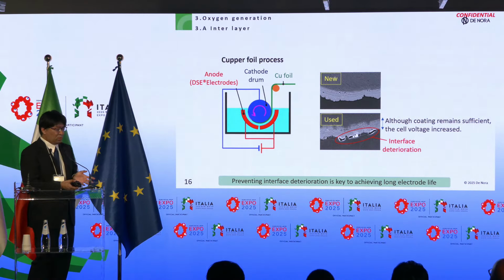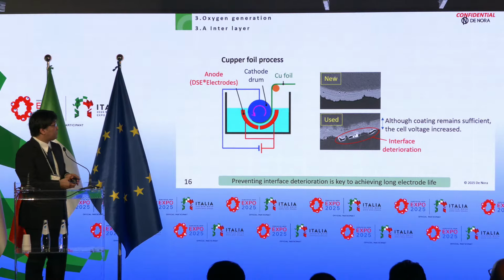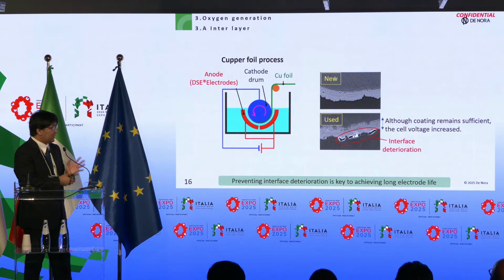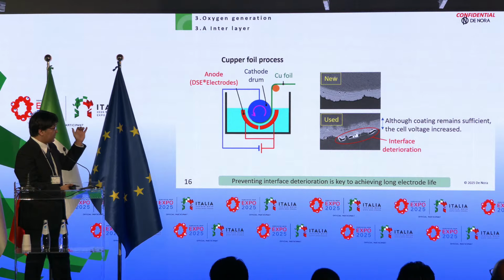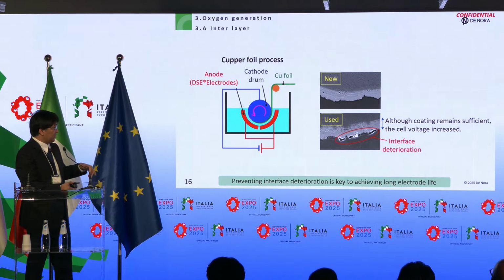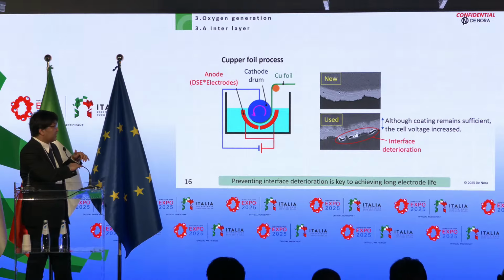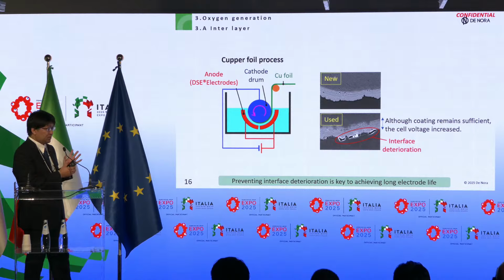In case of oxygen generation, interface deterioration can occur because the electrolyte penetrates into the interface and causes passivation. So although sufficient amount of coating remains, cell voltage can increase. It's different from the chlorine generation anode.